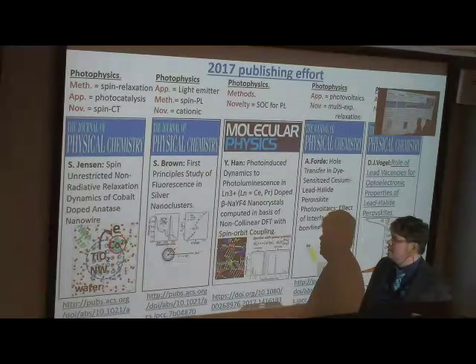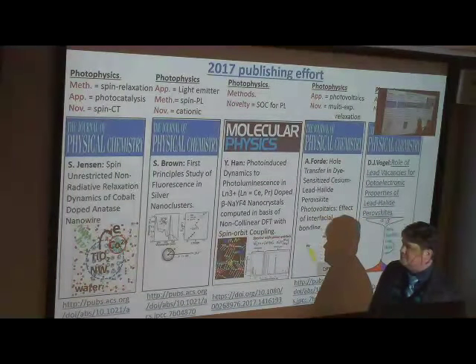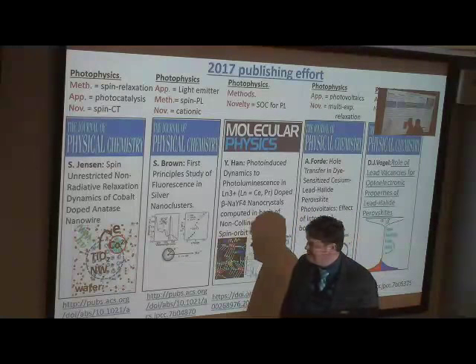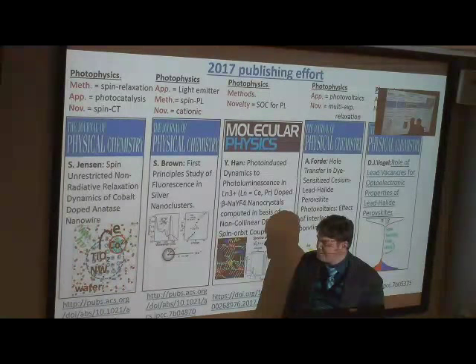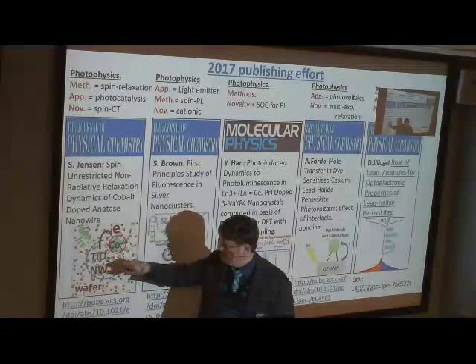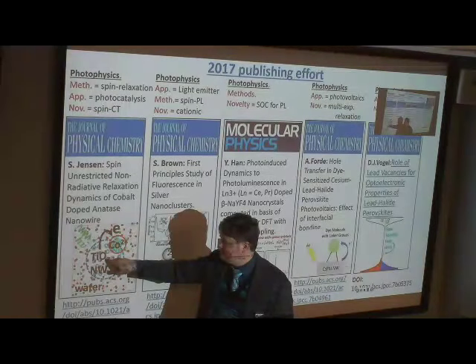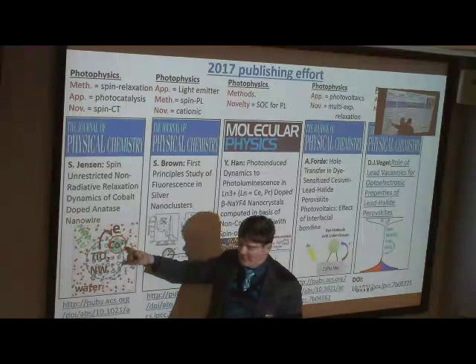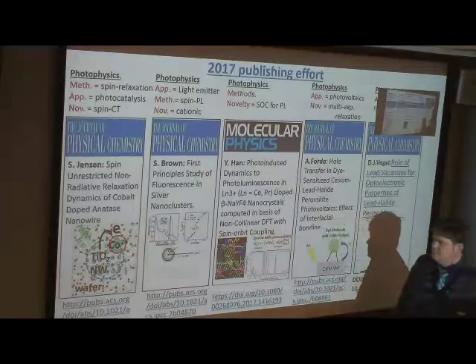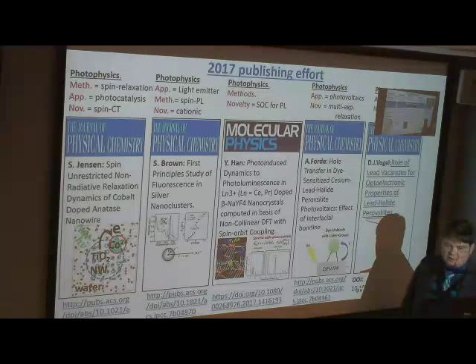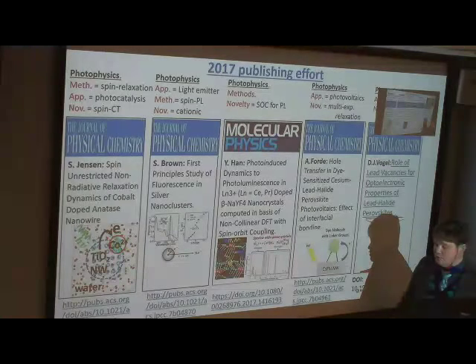So for photophysics, there was a work by Dr. Jensen Stephanie, who is a postdoc at Wake Forest University in North Carolina. This is about a nanowire of titanium dioxide, where we look not along but across the nanowire, getting the photoinduced charge transfer to surface doping, doping of a transition metal. This work was done in the spin-resolved, spin polarized version, having some methodological novelties for processing dynamics when the system is in an open shell configuration, which is important